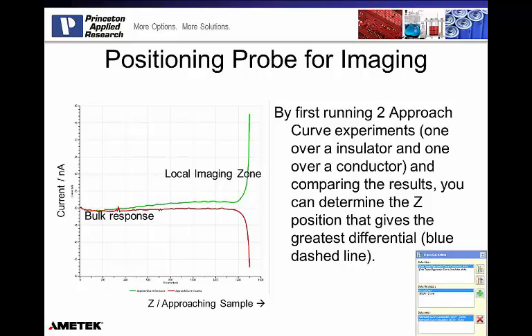So that gives me a very small difference between a highly conductive and a highly insulating response. But you can see this almost asymptotic type relationship as we move into the sampling zones closer to the 1,500 micron response. You can see that you're going to expect in the 30-something nanoamp response over the insulator and the 70-something nanoamp response over the conductor, which is more than a factor of 2 increase in the current response over the insulator and conductor.